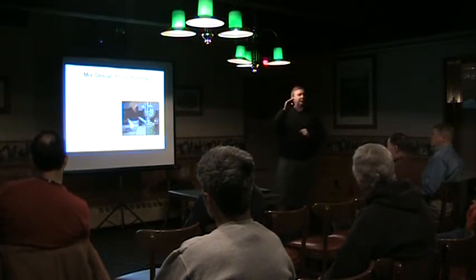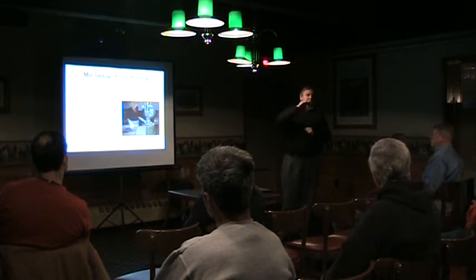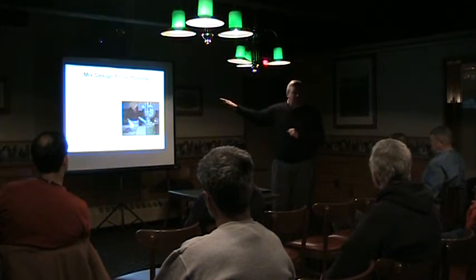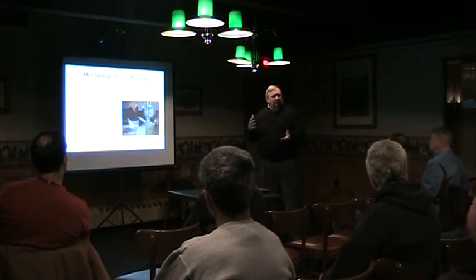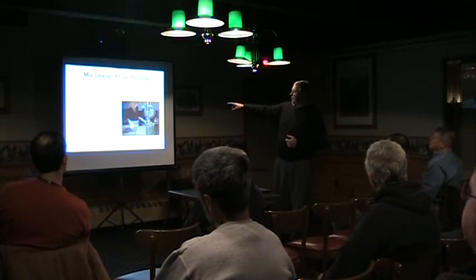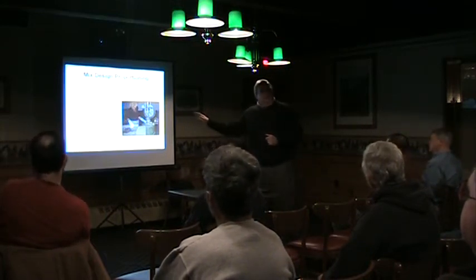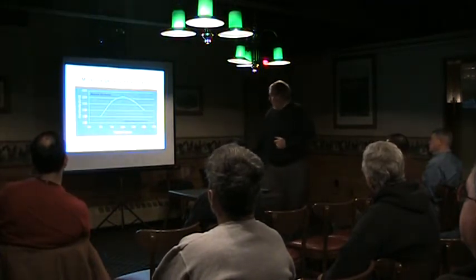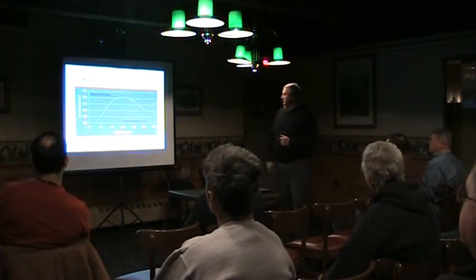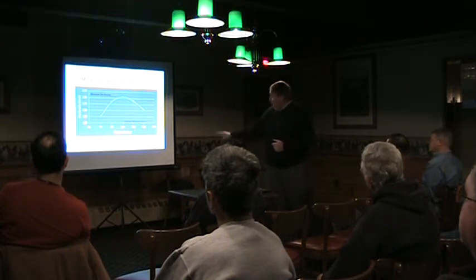We're going to run a moisture density curve because we want the moisture in the field. The moisture in the field will typically be somewhere between 5 and 7%. But we have an optimal moisture where we want to be when we're out there doing this procedure, which is probably going to be somewhere in the vicinity of 11%. And that's where we want to be. So when they do this test, they'll run this at optimal moisture. And then we will do an unconfined compressive strength test. This would be the optimal moisture curve, moisture density curve, which shows it at about 11%.